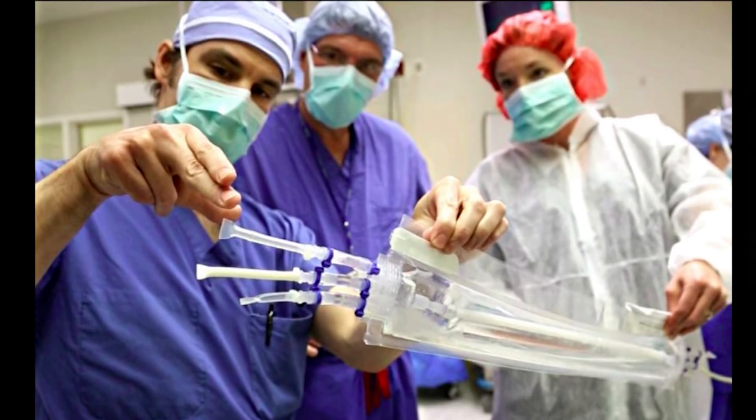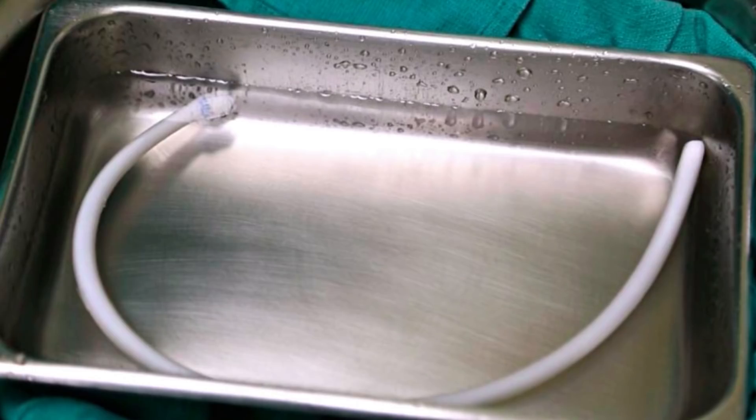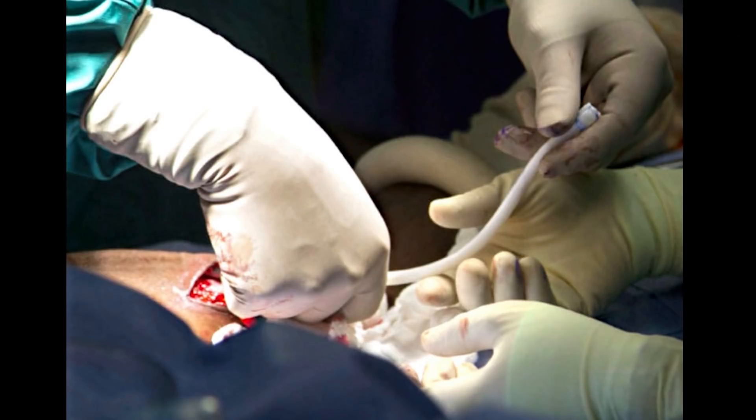Connective tissues really rely on their extracellular matrix constituents for their mechanical function. If we took human cells from young, relatively healthy people, we could coax those cells to attach to the mesh, replicate, and secrete a lot of extracellular matrix to make a mechanically strong tissue. We can seed them into a bioreactor, grow an engineered artery, and then as a final step, decellularize that artery to render it non-immunogenic.